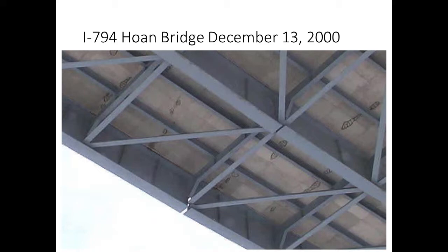And thereafter, there was an investigation. The girders were made out of ASTM A36 steel. Follow-up chemical and mechanical evaluation of the steel, along with Charpy tests, indicated that the steel was acceptable. The other finding of the investigation that was of interest was that these fractures were completely brittle fractures. There wasn't any subcritical crack growth prior to the failures.